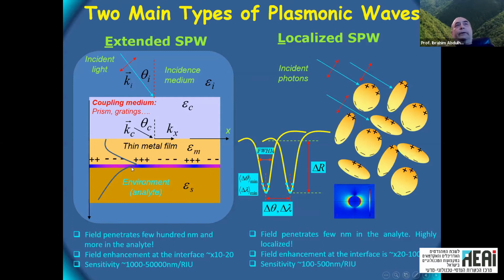But it's a fraction of the wavelength. And because the field is confined, again, here in this direction, we get enhancement near the interface. And this enhancement is something like times 10 to times 20, but it has very high sensitivity in terms of shift of the wavelength of the resonance. It could arrive to 50,000 nanometers per refractive index unit, which is very, very large. It's a huge number as compared to the localized SPR, which is only 100 up till 500 nanometers per RIU.